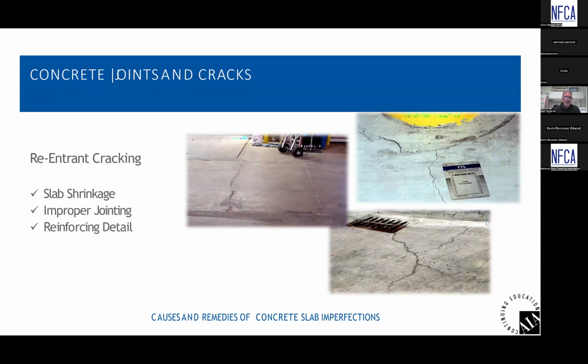Some other concrete cracks that you may see out there could be due to shrinkage or improper jointing or an improper reinforcing detail. The top picture, or the left picture, I should say, we have a joint in the middle top of that picture, and then another concrete slab was poured, and that joint in the adjoining slab, the movement there, caused the concrete to crack in the adjoining pad, as you see in the middle to the bottom part of that left picture.